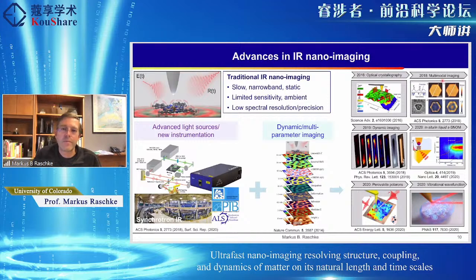We then did, in a number of works, multimodal imaging, where we combined optical scanning probe also with electron and X-ray microscopy. Then a few years later, we were able to do more dynamic imaging, time resolved. And this is where I'll show you a highlight. We did bring IR SNOM into the in situ and in liquid environment a few years ago. What I will also emphasize today is how we image perovskite polarons, the electron-phonon interaction. This is the far from equilibrium pump probe experiments with excited state dynamic imaging. This was achieved just recently for the first time. And I already mentioned the vibrational wave function spectroscopy, which I will not have time to speak about today.